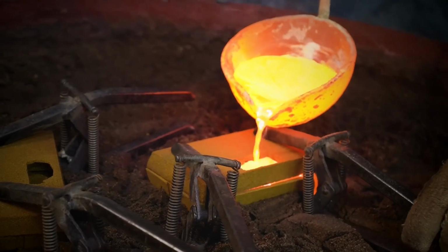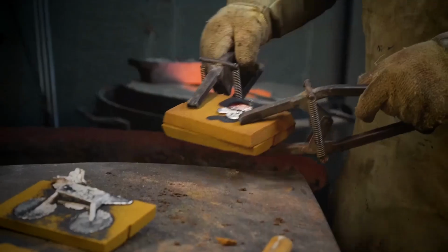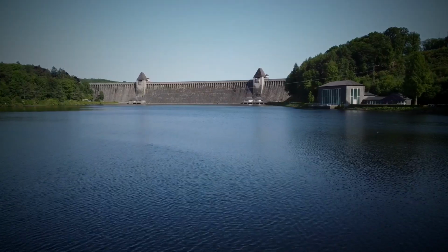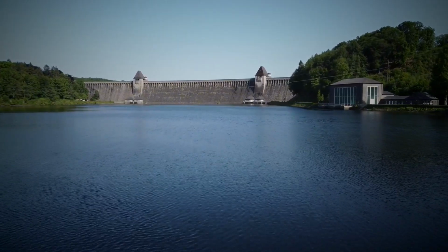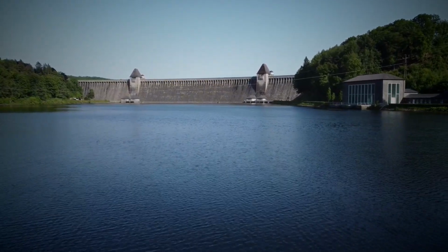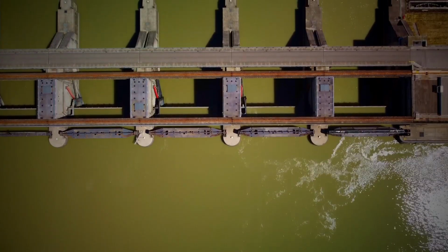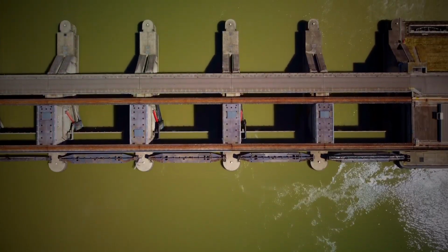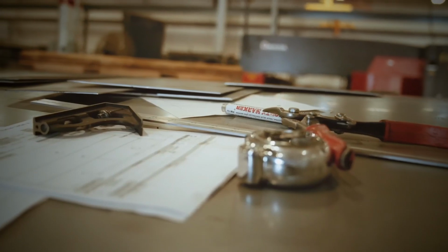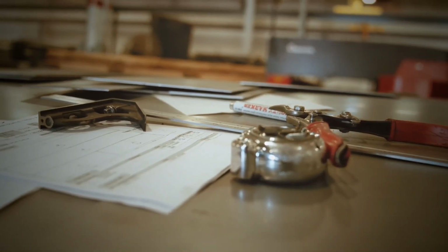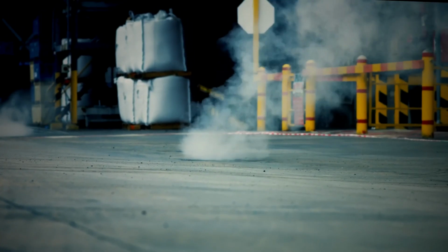One detail that stuck with me going through the industry's failure literature: a huge proportion of structural concrete problems trace back not to the plant, not to the mix design, but to what happened in the last 90 minutes. Water added at the job site to make pouring easier, cure blankets left off in a cold snap, pours made too fast, too thin, into forms that were never properly prepared.